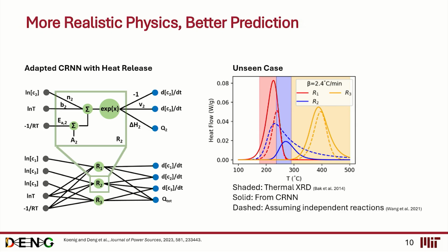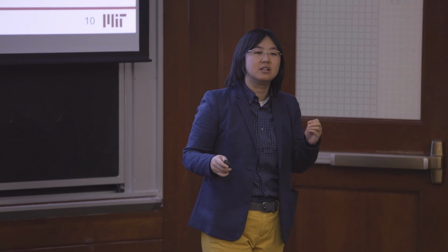With the CRNN approach that Ben developed, applied to the battery case, not only can we be more physical, but quantitatively it also agrees very well with what is experienced and observed by the experimentalists on the critical windows, where we have the 3 stages of the thermal decomposition. And this is really the advantage of embedding physics into the machine learning framework.